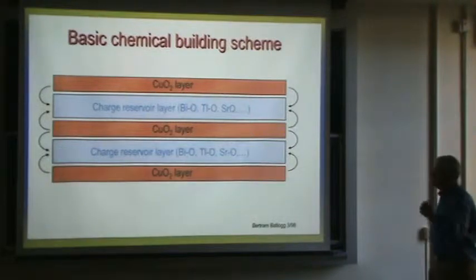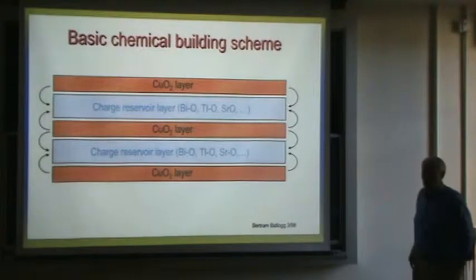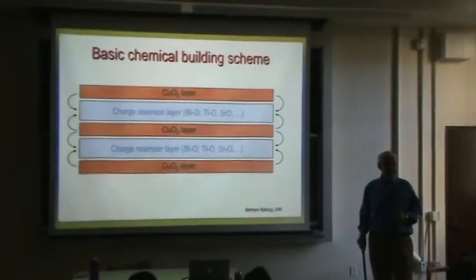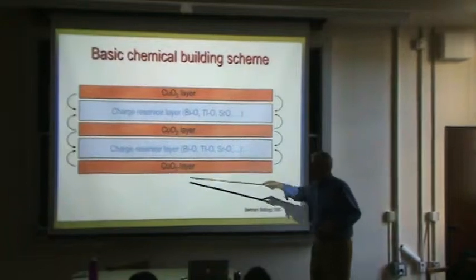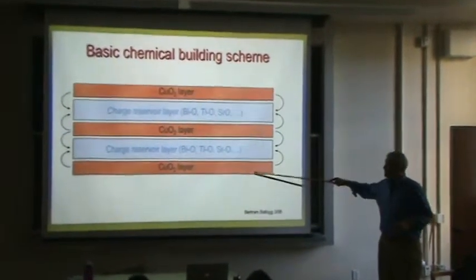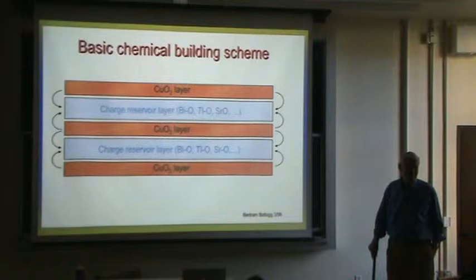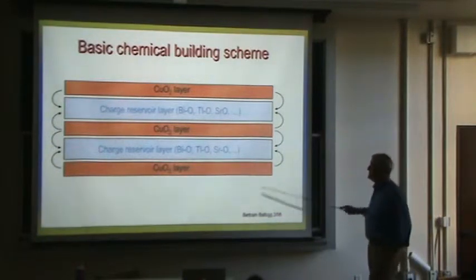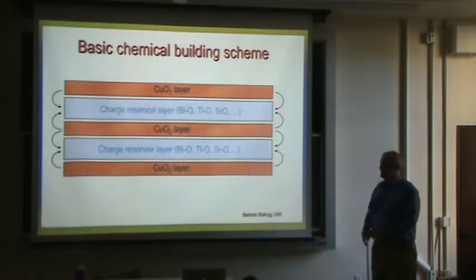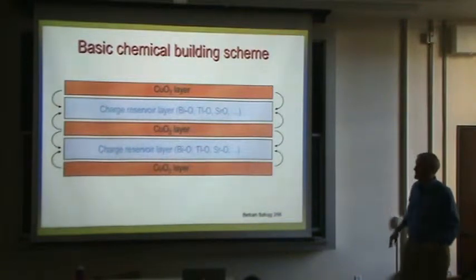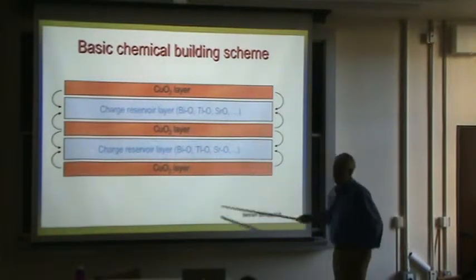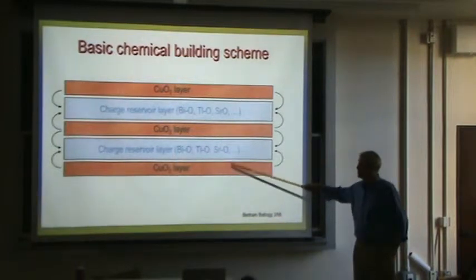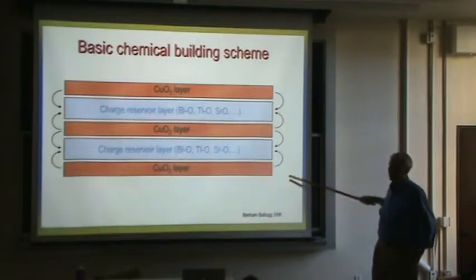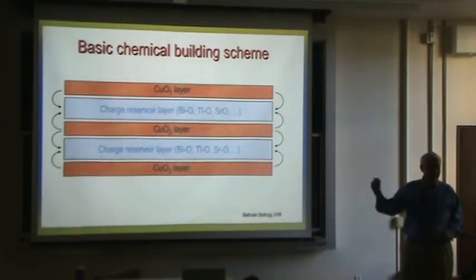So it turns out people did wonderful materials research, and all of the high-temperature superconductors until 2008 had this basic structure, either one or maybe two or three layers of copper oxide. I'll show you that structure in a minute. And then something in between, which separates the layers. That is a charged reservoir layer. This layer is the source of the holes or electrons that fall down into the copper oxide layer and then provide the carriers for the superconductors.